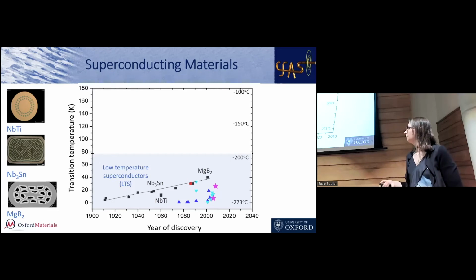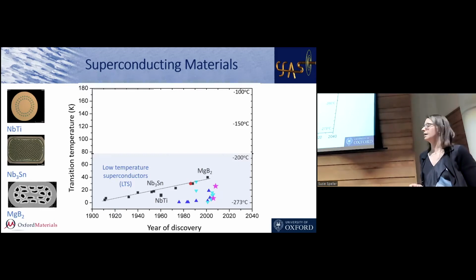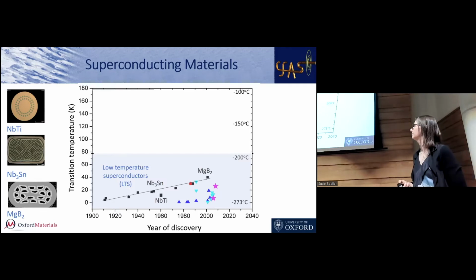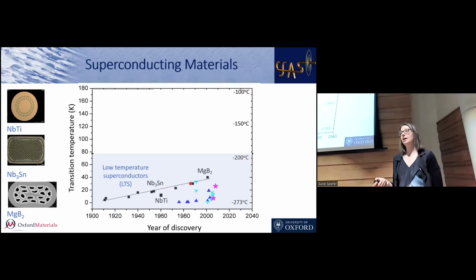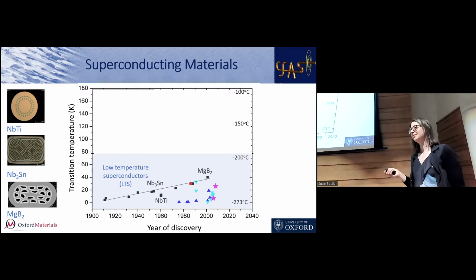During the 1900s, the temperature gradually crept up. There were some other families that were discovered, completely different kinds of superconductors. But the highest one of this series that we found so far was discovered in 2001, so really quite recently, and that's magnesium diboride, a simple binary compound that will superconduct at about 40 Kelvin, so it's pretty good. Now, this is all interesting, but we need to cool these down to temperatures that are pretty low. 40 Kelvin was about the highest. And so nearly everything was using liquid helium, which is an expensive coolant. It costs about the same as whiskey, I'm told. So it's quite expensive.